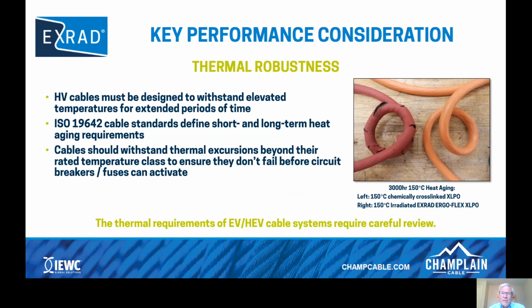We have a rubber cable that was rated at 150 C, but did testing on it for 3,000 hours, and you can see the cracks in the cable, which form a very dangerous situation. As you can see, the XLPO cable on the right aged very well, unlike myself.